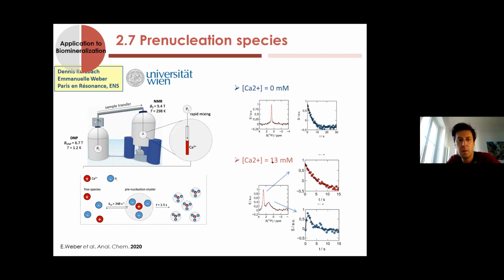But we did some experiments with higher concentrations and with longer time of equilibration, of maturation, let's say. And in that case, you don't need DNP, you just need a good phosphorus probe. There is, for instance, some experiments we made with simulated body fluids, SBF. There is no precipitation; it's a metastable solution. And then you see the transformation also of the phosphorus units, starting from the free phosphorus and then interacting with the calcium over time. But here, the equilibration is very long, about 1 or 2 days. So you don't need the DNP.